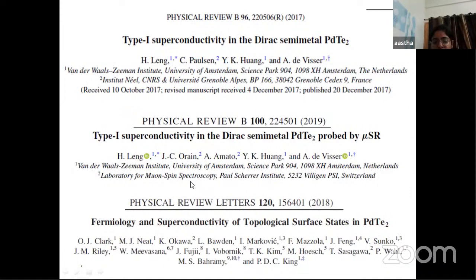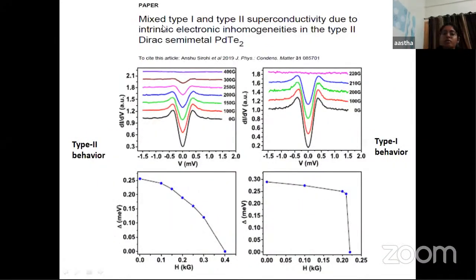So after the discovery of this either type 2 or type 1 superconducting phase in PdTe2, we did STM experiments on PdTe2, and what we found is mixed type 1 and type 2 superconductivity, where the surface of PdTe2 hosts both type 1 regions as well as type 2 regions coexisting on the surface of PdTe2. So what we observed is mixed type 1 and type 2 superconductivity existing on the surface of PdTe2.